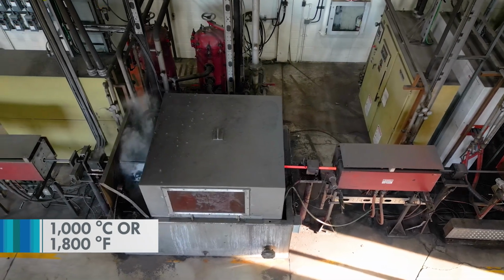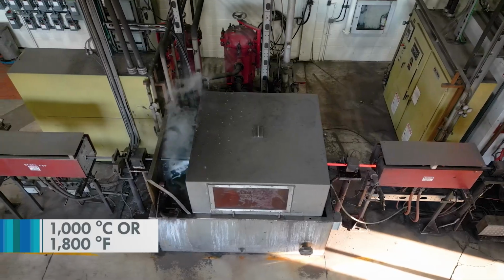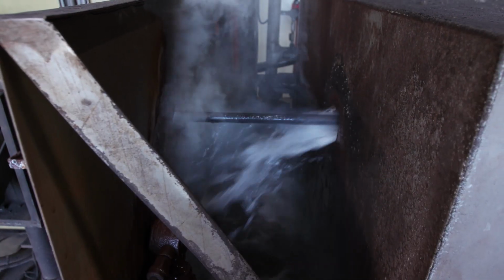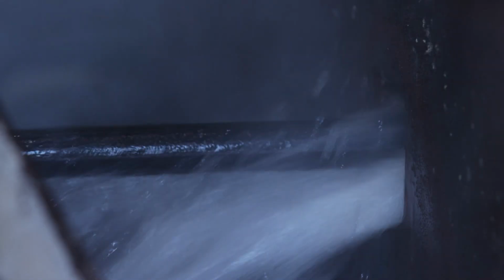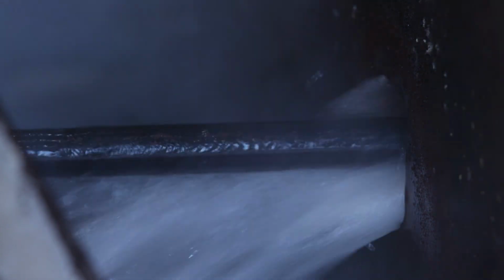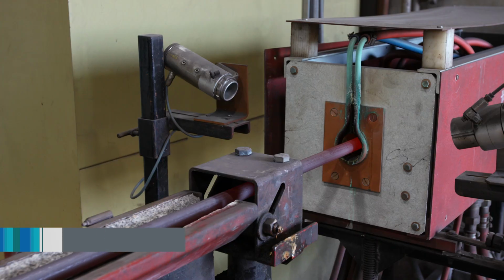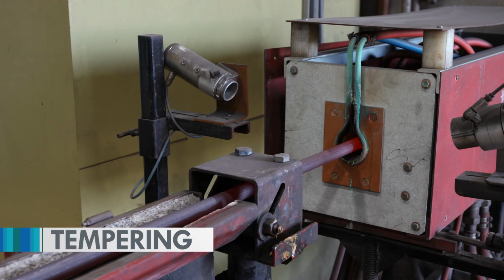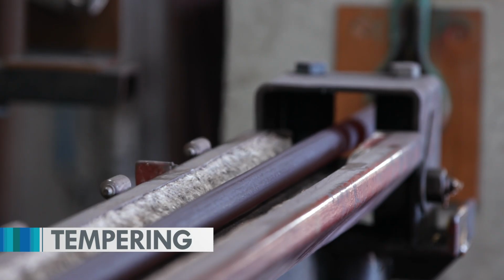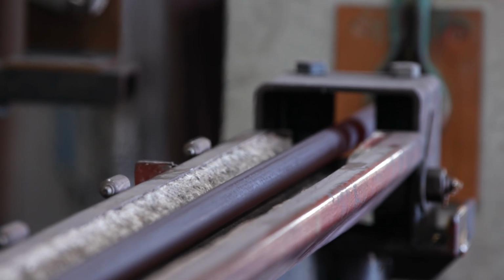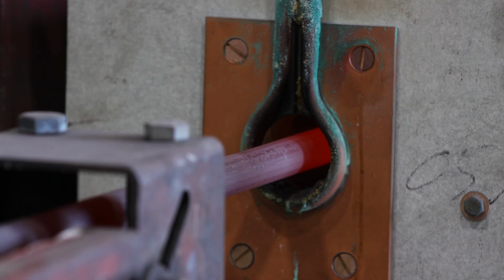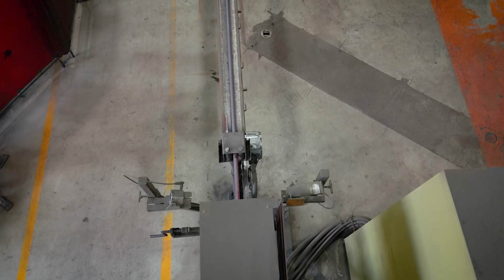The steel is then immediately and rapidly cooled using a water quench process. The quenched rod now has a martensitic microstructure, which is hard but brittle. The second phase of heat treating is tempering, which gives the rod the desired ductility while retaining hardness. The rod is precisely reheated in a second induction heater to achieve the desired balance between ductility and hardness.